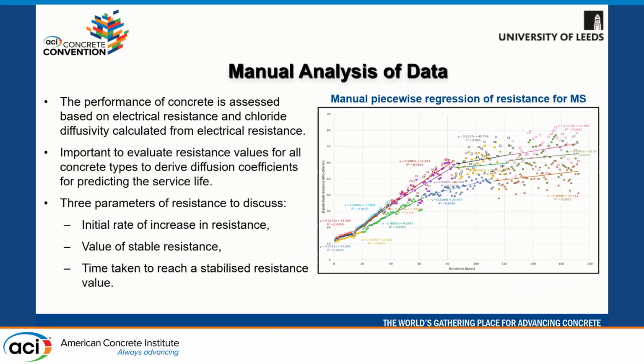So the performance of concrete can be assessed based on electrical resistance and chloride diffusivity that can be calculated from electrical resistance. So it is essential to consider three parameters of resistance for further analysis, that is initial rate of increase in resistance, value of stabilized resistance, and time taken to reach a stabilized resistance value. Shown here in the graph is standardized resistance of microsilica with time.